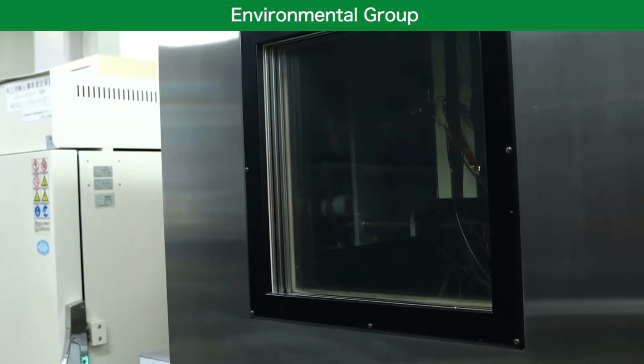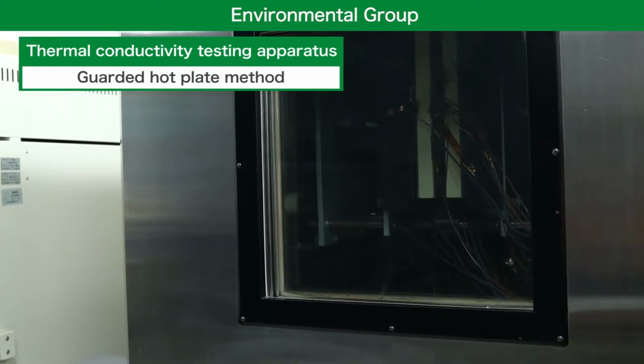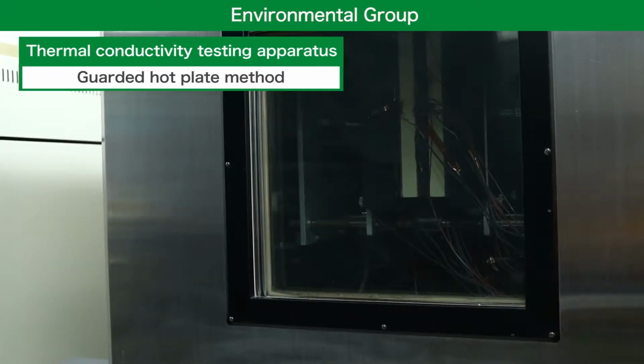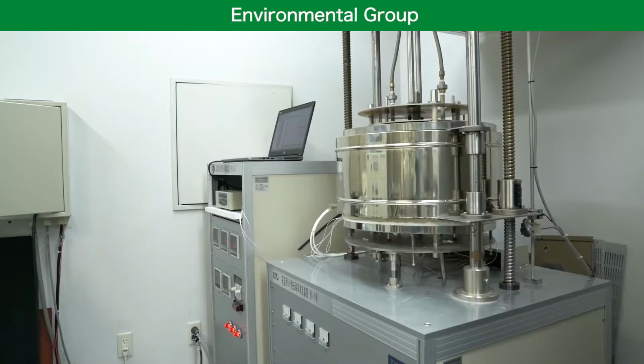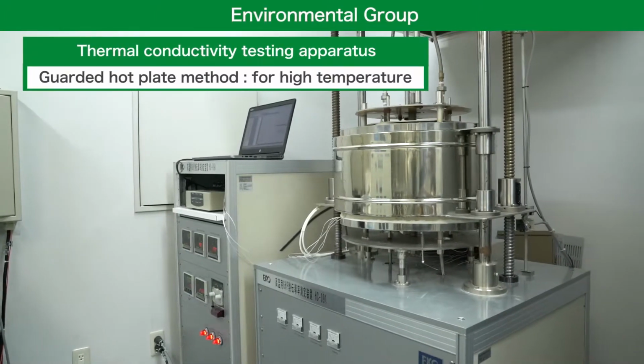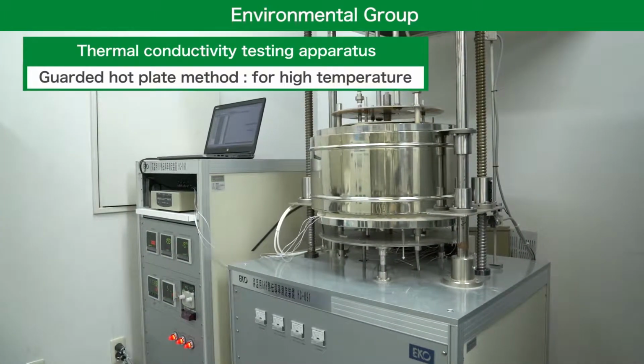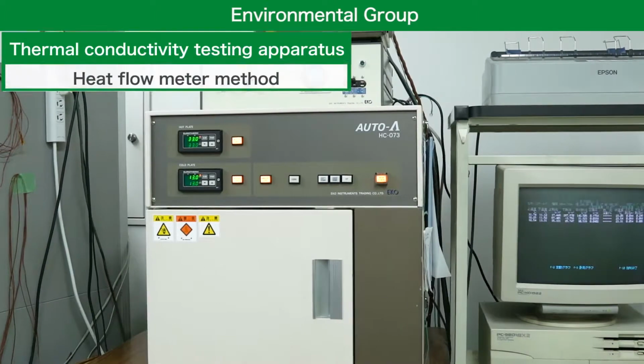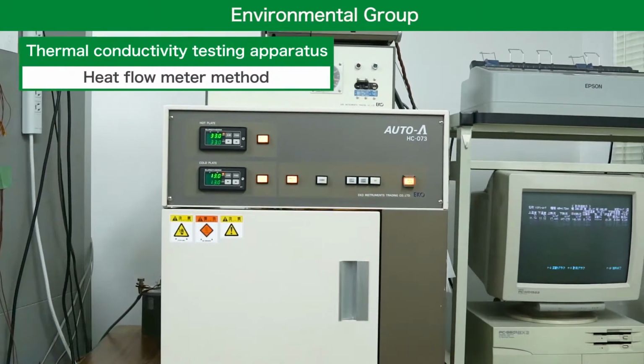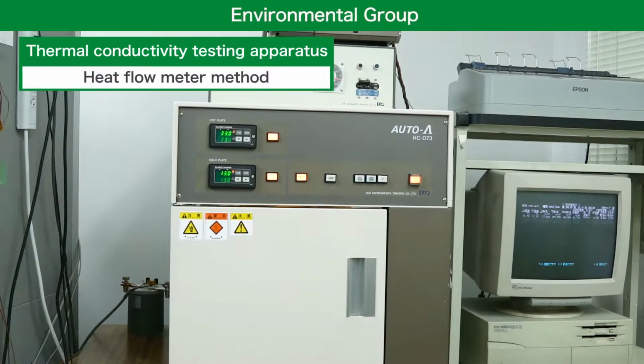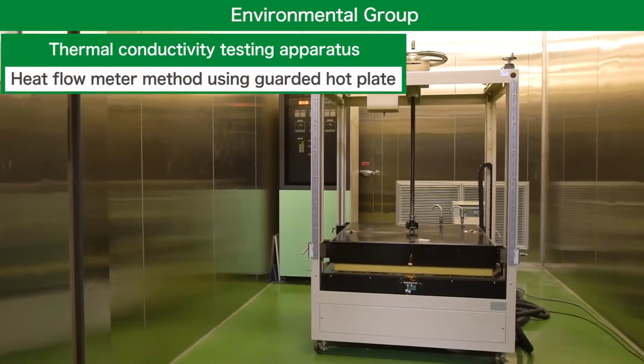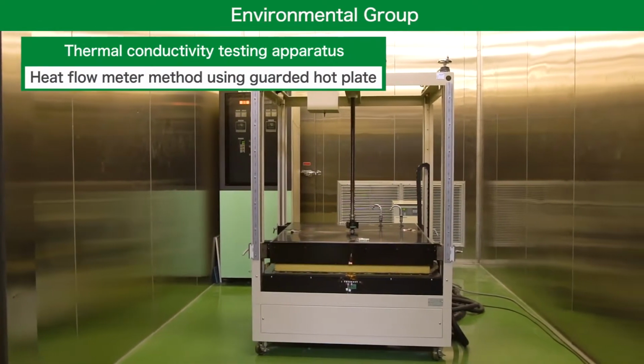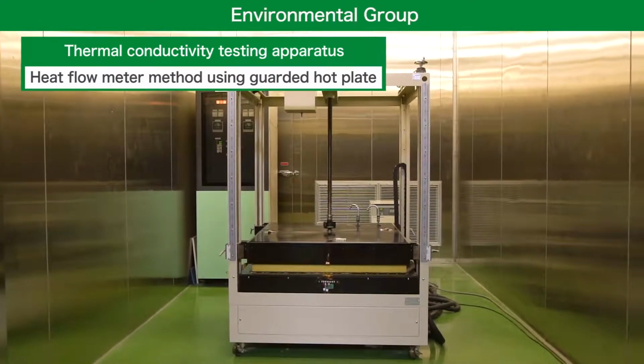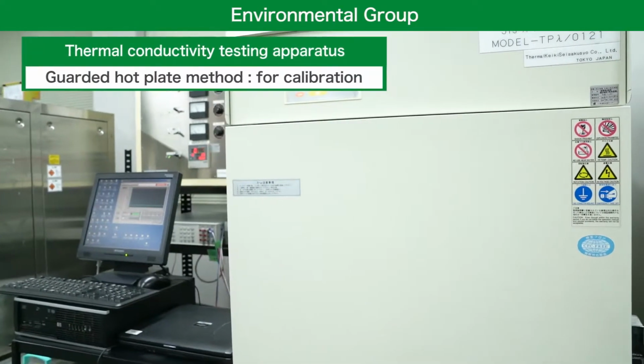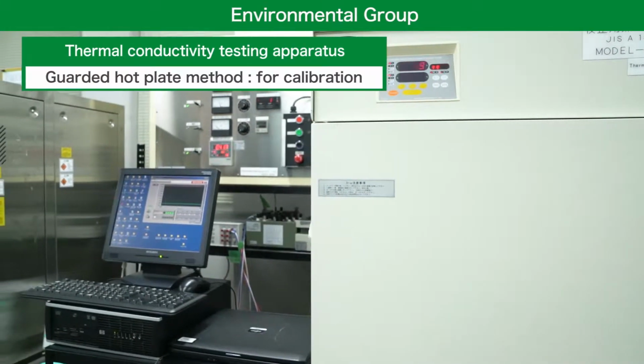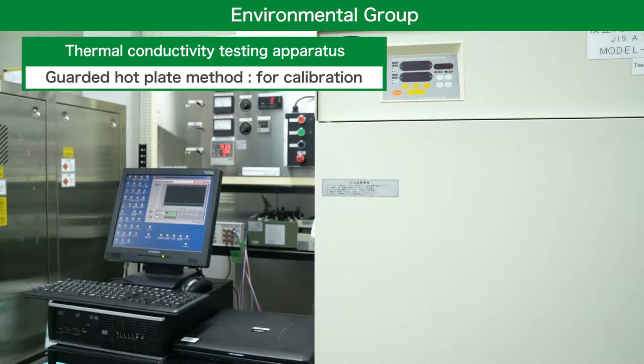A thermal property test room is used for thermal property tests of the construction materials such as thermal conductivity, specific heat and coefficients of linear expansion. Among these, thermal property tests are performed with 2 sets of instruments for the guarded hot plate method and 5 sets of instruments for the heat flow meter method, allowing for measurements at various temperatures and thickness of test pieces. Calibration test services are conducted here, as it is the only existing institution for thermal conductivity calibration in Japan.